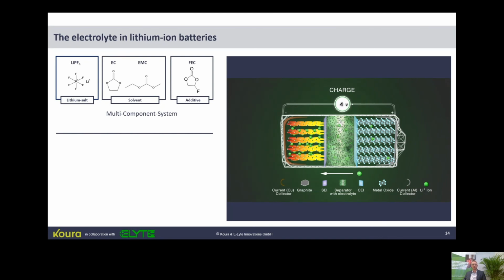But more important, or maybe equally important, is that we have the formation of a passivating surface layer. On the one hand side, this is the very prominent SEI, the solid electrolyte interface on the negative electrode, and also the CEI, the cathode electrolyte interface on the positive electrode. Without these interfaces, the battery would not be able to survive. These interfaces are mainly composed of electrolyte decomposition products, which are not soluble in the electrolyte. So they precipitate on the surface of our active materials and protect the bulk electrolyte from further decomposition.